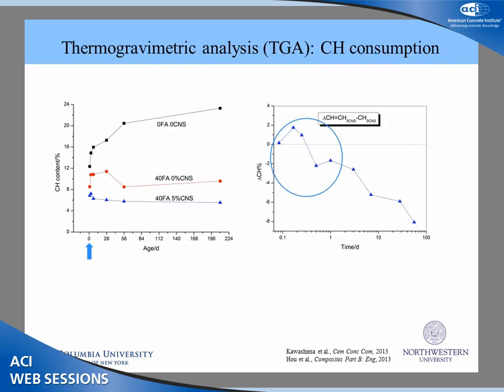So to better understand this, we looked at CH consumption through TGA. This is CH content with respect to time. Now for plain cement paste, the CH content just continues to increase due to the progression of hydration. Now with 40% fly ash replacement, there is an initial increase, but then it goes down because the fly ash is continuing to participate in pozzolanic reaction. And with the addition of 5% colloidal nanosilica, CH content goes down even further. And again, that's because colloidal nanosilica is also a pozzolanic material.